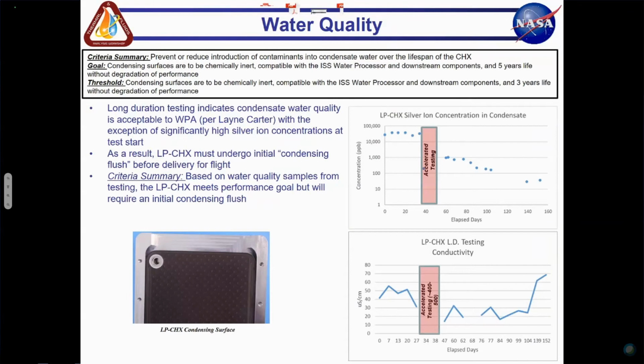So we could really tell right up front whether we were going to get any adverse effects from the testing air that we were using, which is just a lab environment, but also stuff coming off the heat exchanger. And we worked pretty closely with Layne Carter at Marshall to look at our water quality. And we looked through pages and pages of water quality data from this. And basically everything looks acceptable to the WPA for the environment that we were testing in, except we have a gigantic, just a massive concentration of silver ions when we first start testing the laser process heat exchanger.